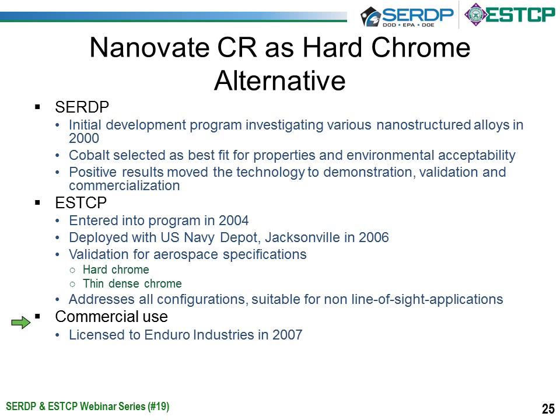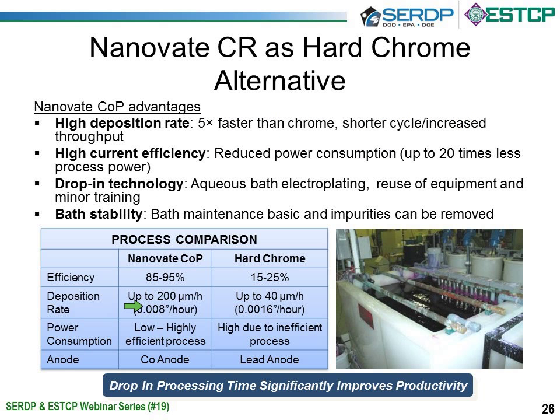And then it has also been used commercially. It was licensed to Enduro Industries in 2007. So the main advantages of the Nanovate CR, which is a nanocrystalline cobalt phosphorus alloy as the hard chrome alternative, are the high deposition rate. It's a very fast process, and in fact it's 5 times faster than chrome, which can result in shorter cycle for processing time and increased throughput.